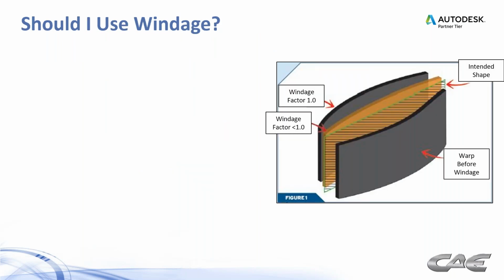Then another thing that might be coming into your head here is, should I use windage? We've done webinars on windage before. For those who don't know what windage is, it's basically biasing the tool steel in the opposite direction of the expected warpage, expecting that warpage to come back to flat. And we talked about when to use it, using it when tolerances are reasonable. For example, if you have a tolerance of 0.1 millimeter on a bumper fascia, that's a tough sell when it comes to changing your mold with windage to reach that kind of tolerance.